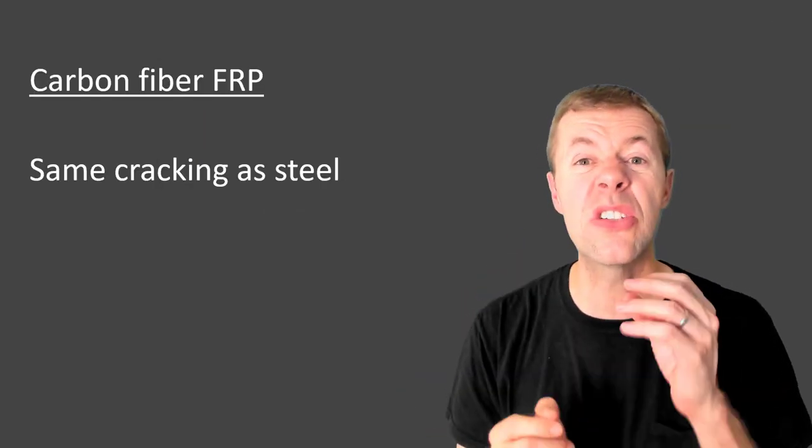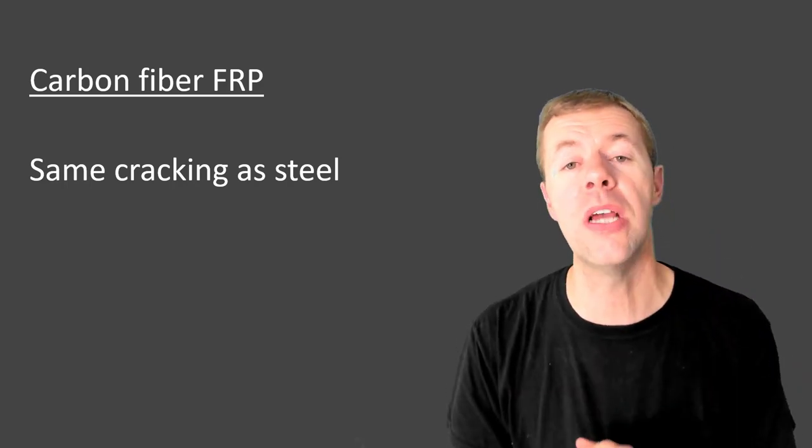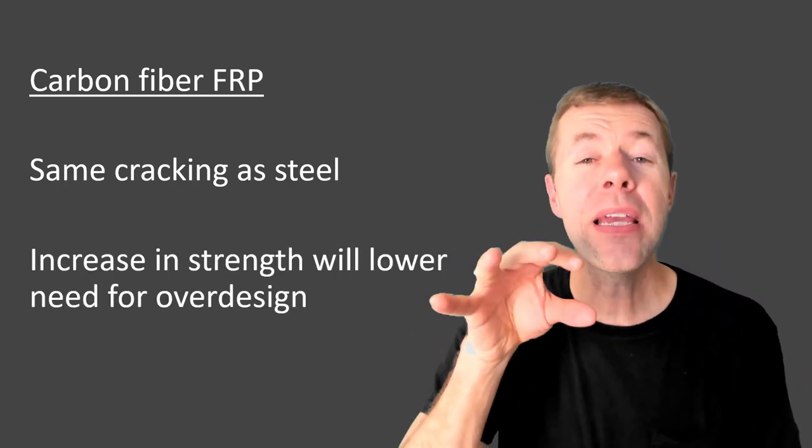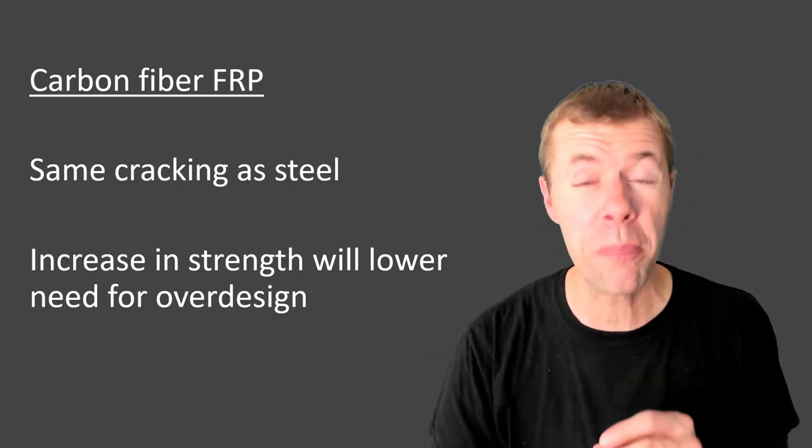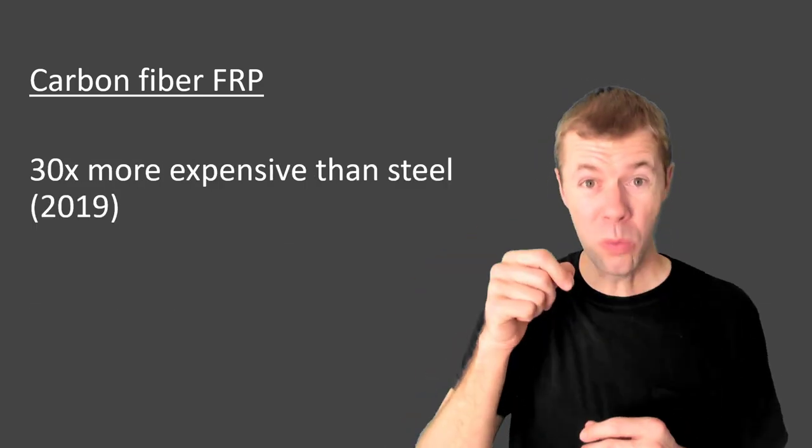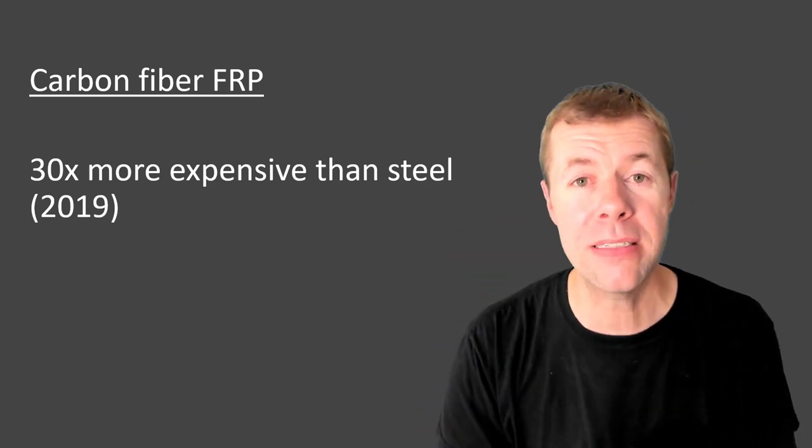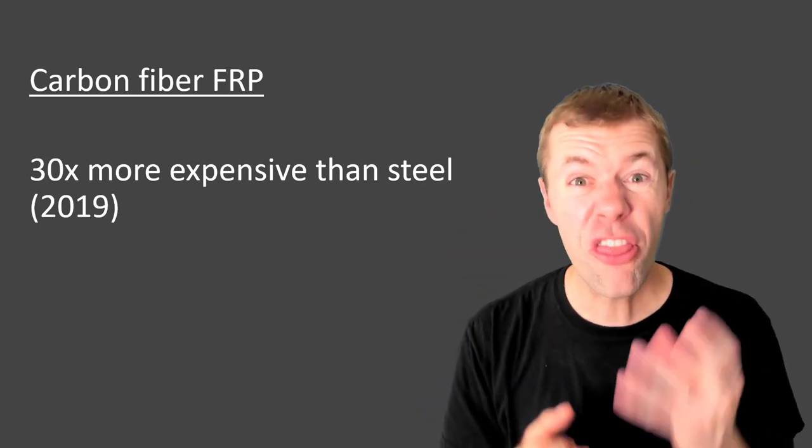Because the slope is the same as steel, you'll get the same cracking performance as steel. And this increase in strength means there's a lower need for over design. I think carbon FRP has huge potential for reinforced concrete. But right now, in 2019, it's 30 times more expensive than steel bar. 30 times more expensive. Oh baby. That's expensive.